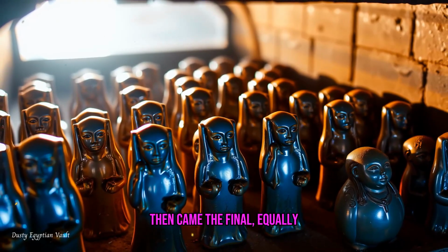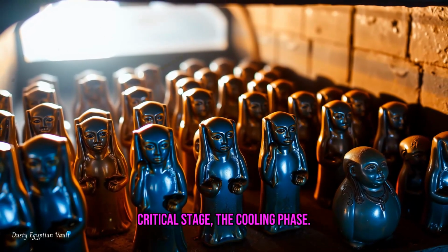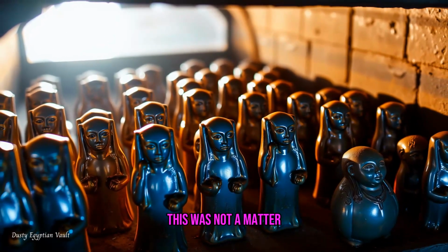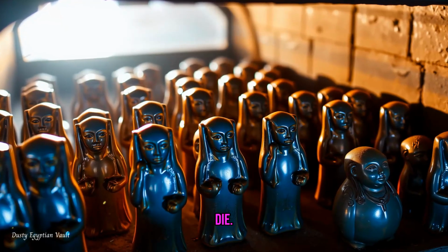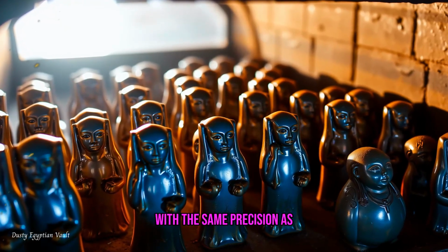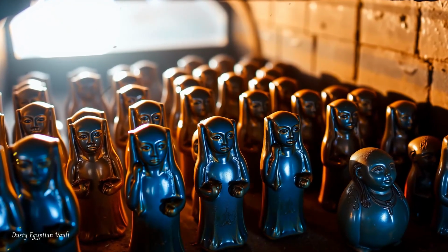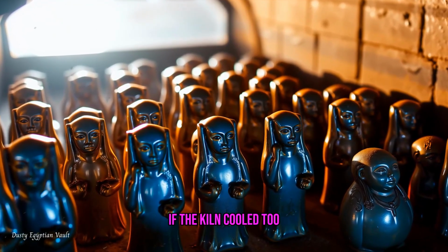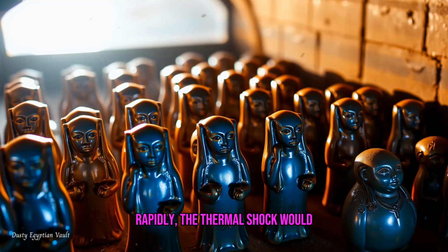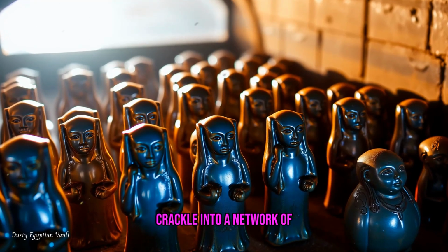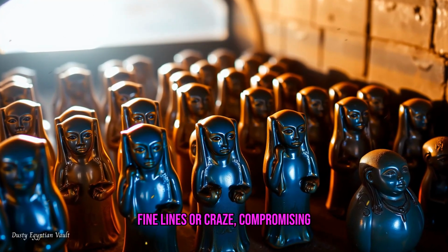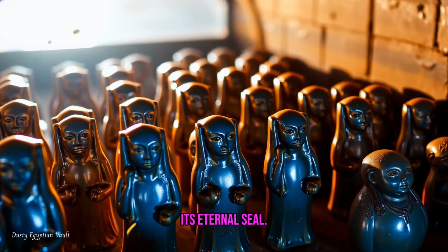Then came the final, equally critical stage, the cooling phase. This was not a matter of simply letting the fire die. Cooling had to be controlled with the same precision as heating. If the kiln cooled too rapidly, the thermal shock would cause the glassy skin to crackle into a network of fine lines or crazing, compromising its eternal seal.